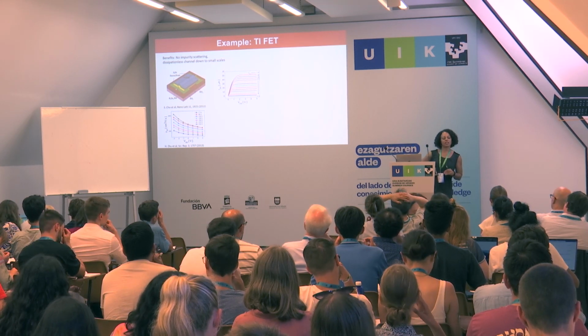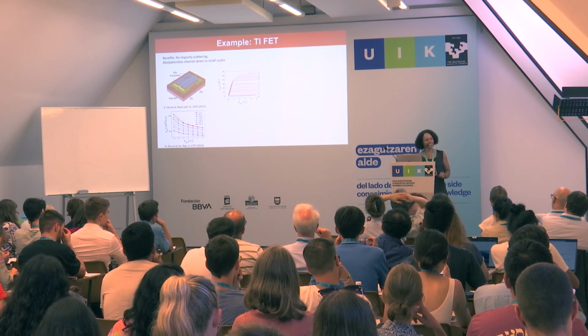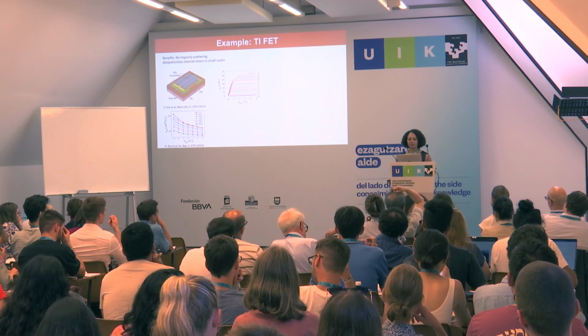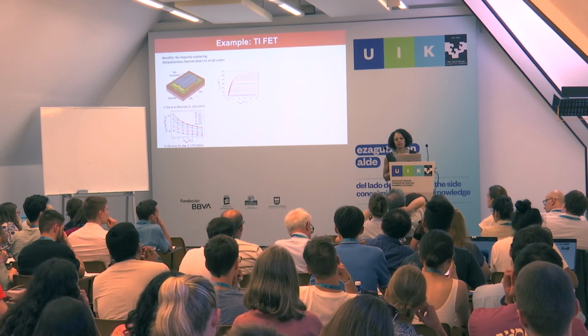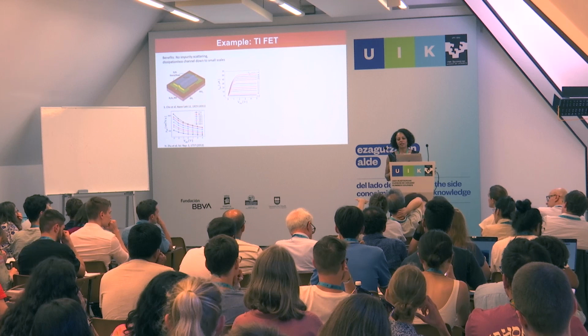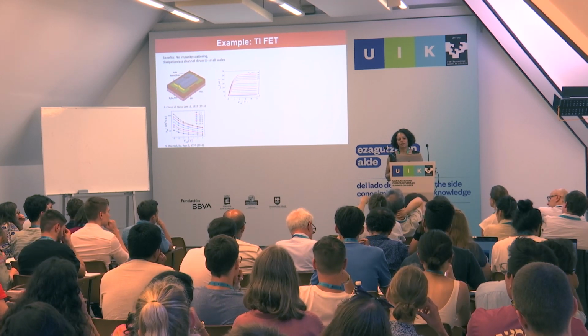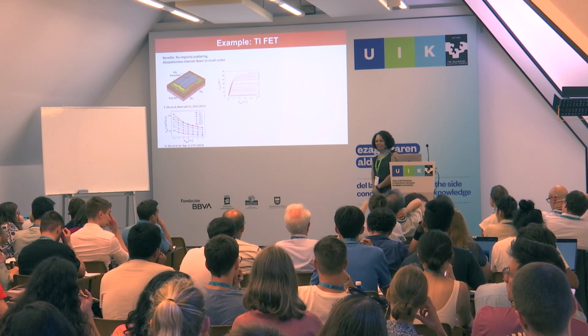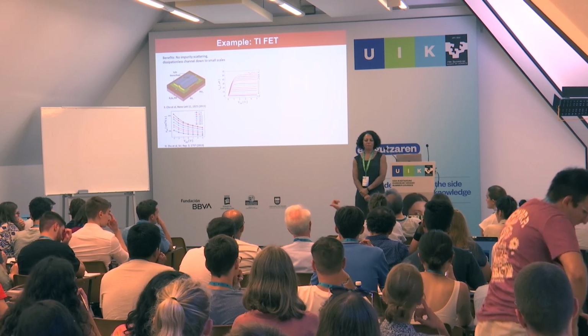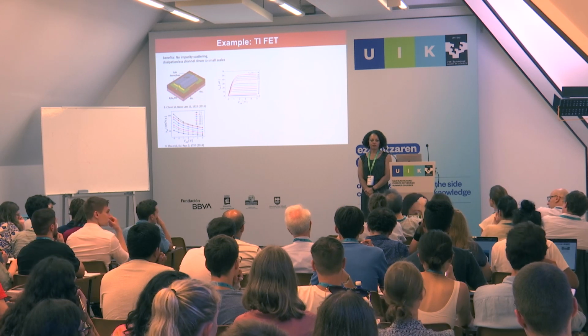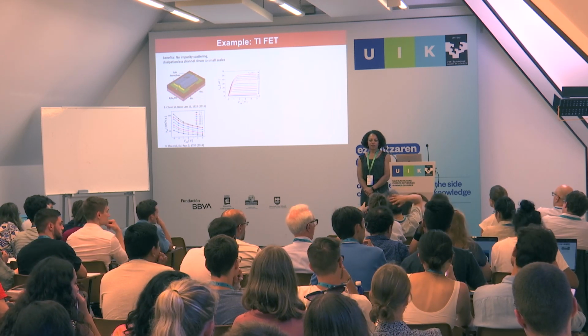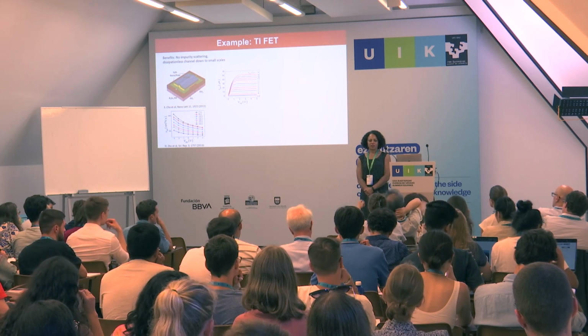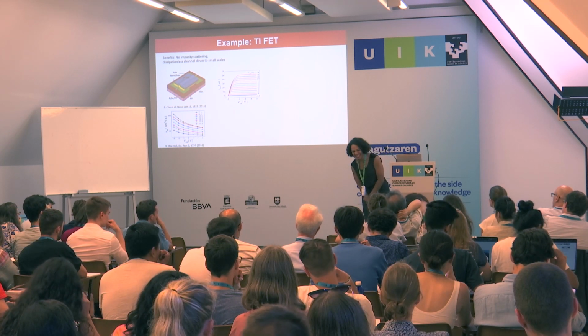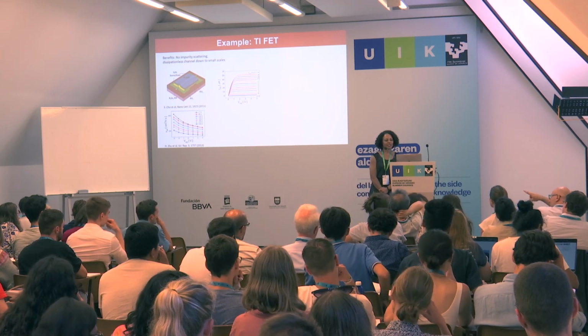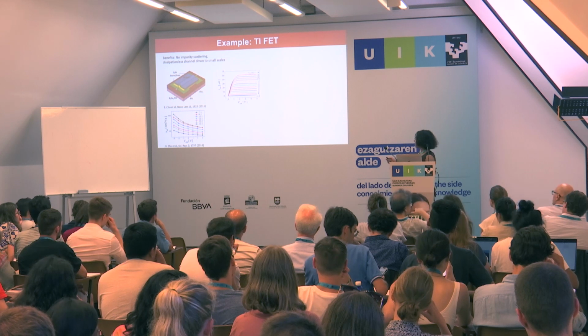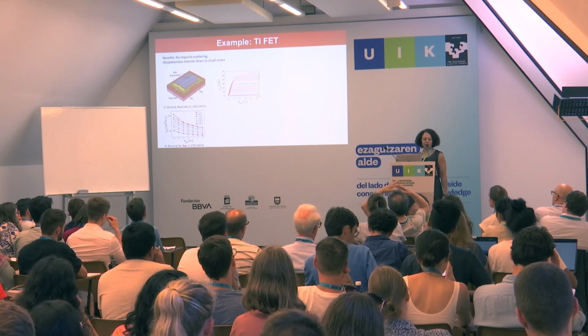In this case, it is phonons that are actually limiting you, which is different from what happens in a semiconductor. Actually, this notion that the backscattering is quenched, it's not really valid. That's my opinion. I agree. If you look at it very carefully, it scatters 90 degrees, because it's not an edge state. Yeah, I agree. You always find it very disappointing. Exactly. But this is a 1D channel. It's not a surface. It's a nanowire, but it's still